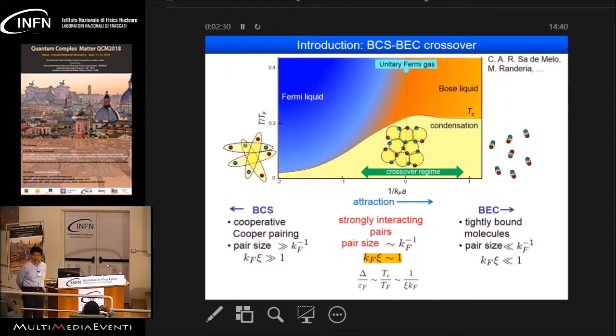Okay, so let me start with the introduction on the BCS-BEC crossover. I'm sure you have seen this kind of phase diagram many times during this conference. Here is the critical temperature divided by the Fermi temperature as a function of strength of attraction. In the weak coupling limit, we have a BCS state, and here the pair size or coherence length is much longer than the inter-electron distance, which is of the order of 1 over kF. So we have a situation where kF xi is much larger than unity.